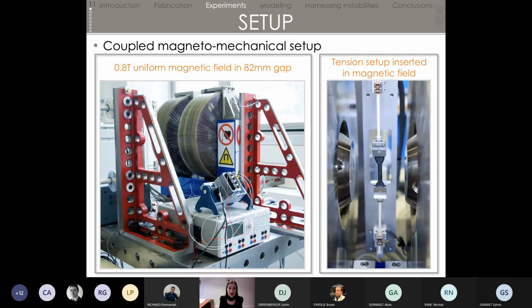So it revolves around a large electromagnet, which can produce a 0.8 Tesla uniform magnetic field in a fairly large gap, 82 millimeters. The reason for having such a large gap is twofold. First, we wanted space to put our molds and to proceed to curing under magnetic field. And the other point is to be able to insert a tensile setup inside that magnetic field. So you can see on the right.